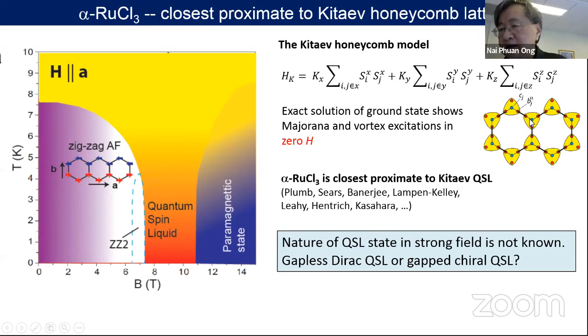So in the Majorana representation, you replace each spin local moment with 3 red Majoranas, which are called B's, and 1 in blue called C. Then you can solve this exactly, and the exact solutions show that the excitations from the ground state are either vortices called visons or these Majorana excitations. But this is for zero field. So in zero field, the system is gapped, right? Gapped to spin excitations. And Kitaev went on to show that you have edge states running in the perimeter. And that might give rise to the quantized Hall effect, quantized thermal Hall effect. But it's important to realize that the bulk is gapped to spin excitations, leaving chiral edge states that are ungapped.